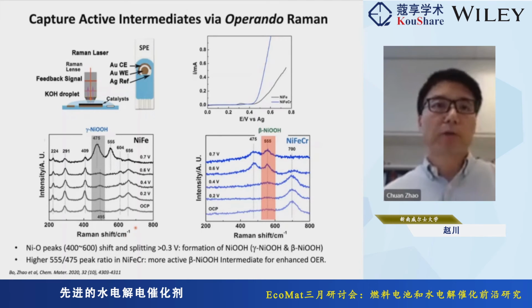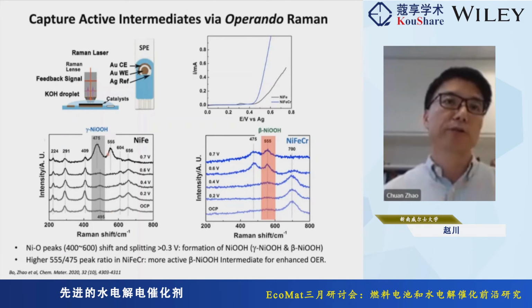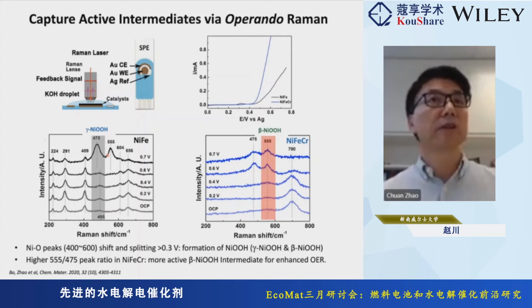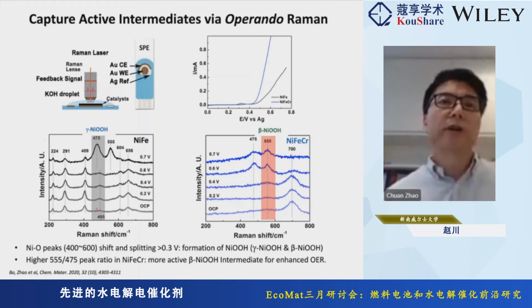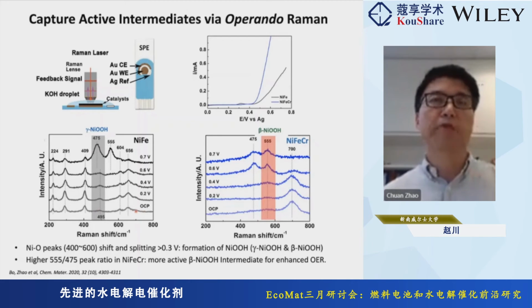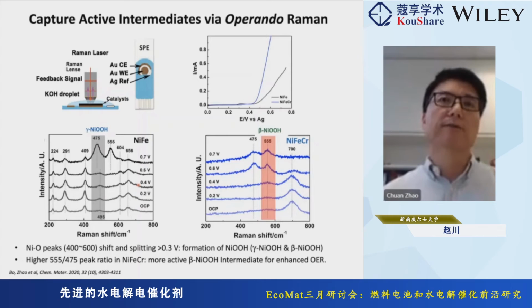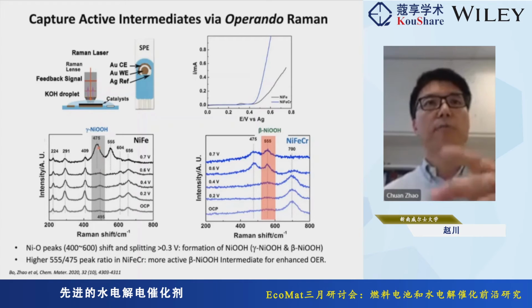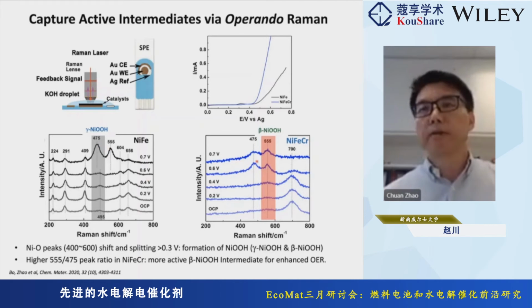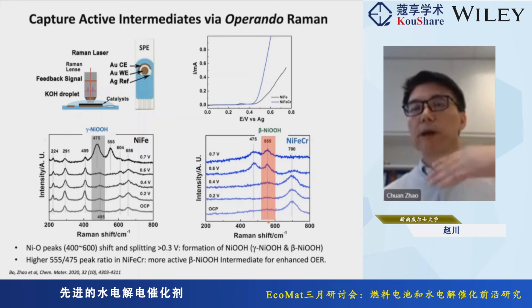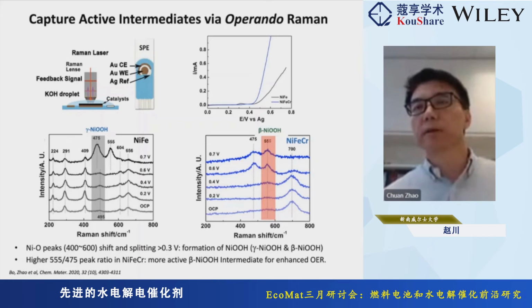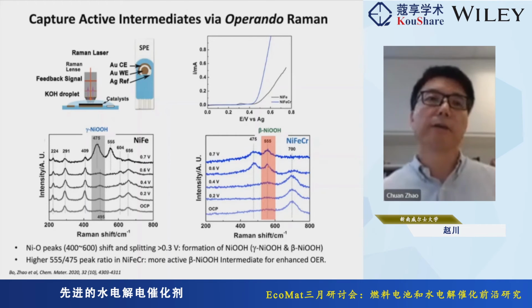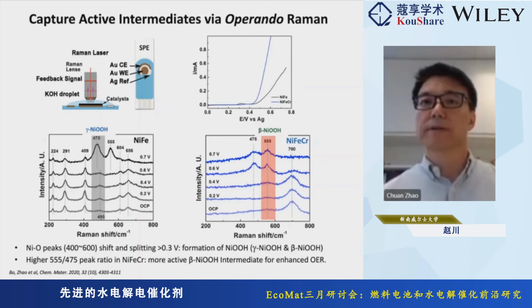So we can actually say, for example, in the nickel iron case, there are 2 characteristic peaks corresponding to the beta phase and the gamma phase of nickel oxyhydroxide, and we can see with the applied potential, the nickel iron catalyst starts to evolve the gamma phase nickel oxyhydroxide, and it has a stronger peak compared to the beta phase. In comparison, when we introduce chromium into the system, we notice that when we apply the potential, the beta phase becomes the dominant phase in the nickel iron chromium system.